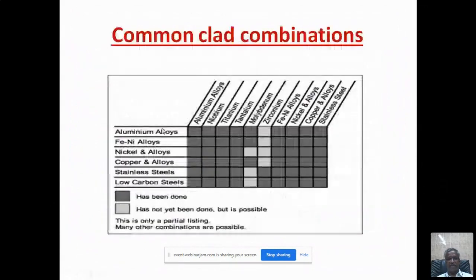So these are the combinations of clads. The black regions are already joined, aluminum with aluminum, aluminum with nickel, aluminum with copper, they are joined. Only these white regions are not yet joined, not yet explored, and if one is interested in explosive welding, you can think of joining aluminum alloy with zirconium, copper alloys with zirconium, stainless steels with molybdenum.